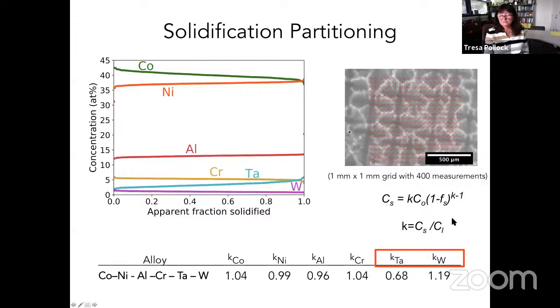And the important parameter here is the partition coefficient, which is the ratio of the concentration of the solute in the solid, so in early solidification, compared to the concentration of the solute in the liquid. And so for this alloy shown here, and I should say that when the partition coefficient is far from 1, we will obviously have strong segregation to either the dendritic or interdendritic regions. And this can create opportunities for convective instabilities or cracking. And so one would really like to have as little segregation as possible.